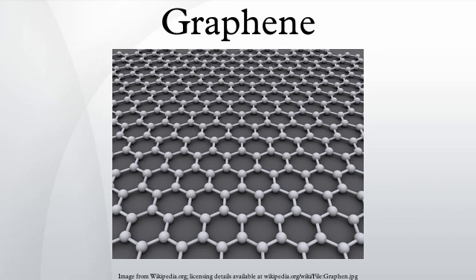Silicon carbide. Heating silicon carbide to high temperatures under low pressures reduces it to graphene. This process produces epitaxial graphene with dimensions dependent upon the size of the wafer. The face of the SiC used for graphene formation, silicon or carbon terminated, highly influences the thickness, mobility and carrier density of the resulting graphene. Graphene's electronic band structure was first visualized in this material. Weak anti-localization is observed in this material, but not in exfoliated graphene produced by the drawing method. Large, temperature-independent mobilities approach those in exfoliated graphene placed on silicon oxide, but are lower than mobilities in suspended graphene produced by the drawing method. Even without transfer, graphene on SiC exhibits massless Dirac fermions.